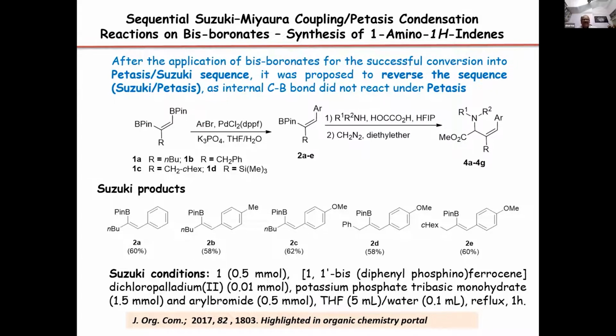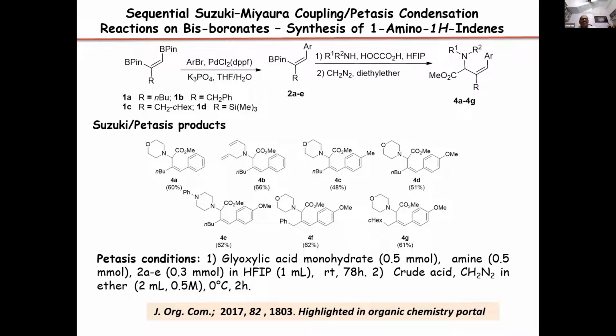Next, please. These Suzuki products are then subjected to Petasis reaction using standard reaction conditions in hexafluoroisopropanol solvent. To our surprise, interestingly, with a very long duration of time, around 78 hours of reaction time, the internal C-boron bond also has reacted and formed the Petasis product to give the amino acids in very good yields. Next.